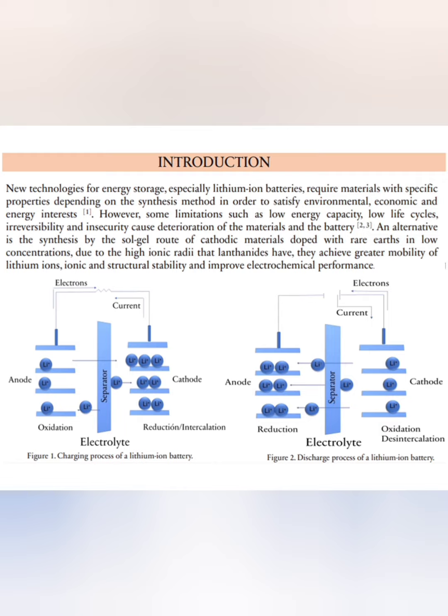In this sense, the cathode material requires a layered hexagonal structure with the space group R-3m, and fine, uniform, homogeneous particles without impurities. A cathodic material used since the 90s has been lithium cobaltate, produced by the company Sony Energy. It presents some limitations, such as cationic mixing due to the similar ionic radius of each element that composes the material, structural change from layered to spinel type, low experimental capacity, and chemical instability, reasons why they deteriorate the battery, causing irreversibility, insecurity, and low energy capacity.